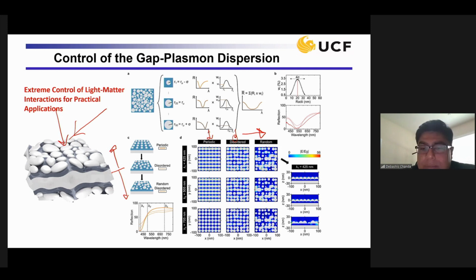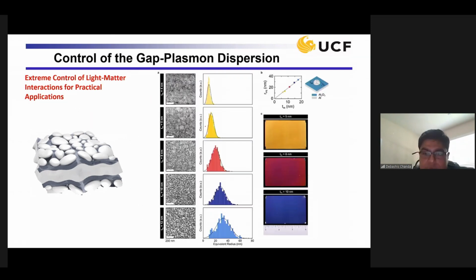Again, for the physics part, for the sake of time, I do not have time, but if there's a paper link, I'll show it at the end of my talk. This is basically a physics problem of how you confine light. You can see the light is confined as a gap plasmon between these two nanoparticles, so it is basically trapped in between. That's the mechanism. You trap the photons between these 1-2 nanometer gaps of the aluminum nanoparticles, you absorb that portion of the spectrum, and the remaining portion comes back up and gives you the color. By changing the gap between them, you can tune the gap plasmon resonance to cover the whole color palette. That's what's shown here.